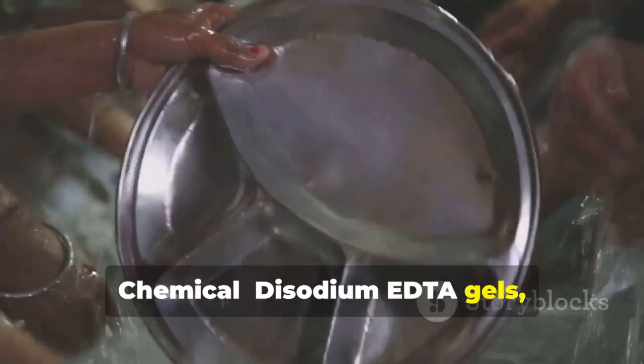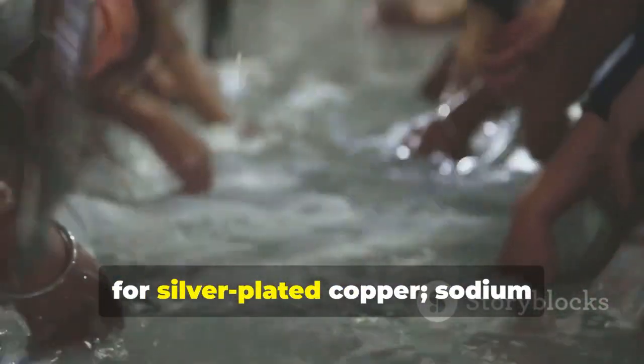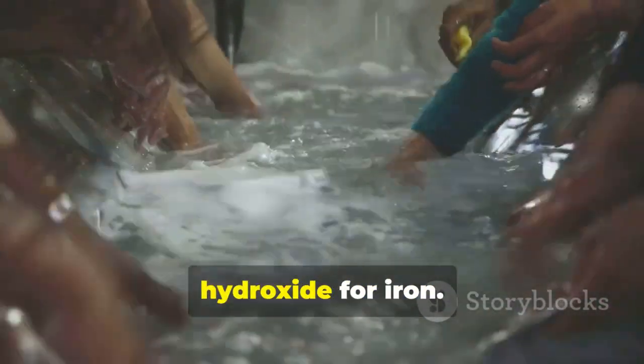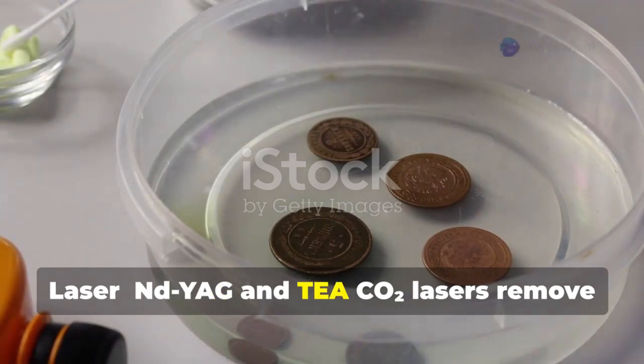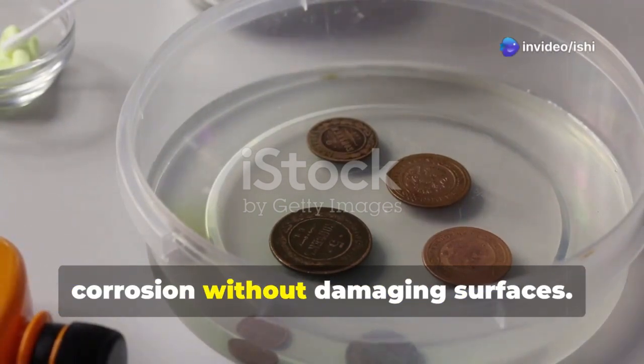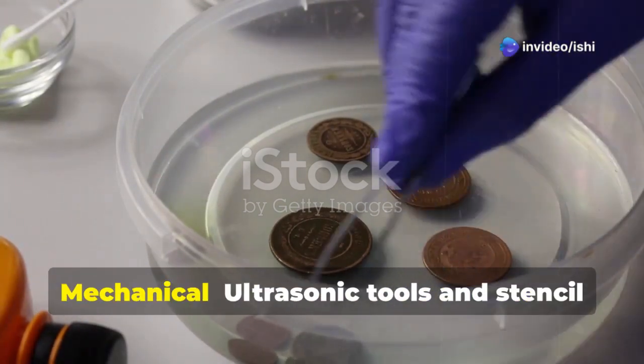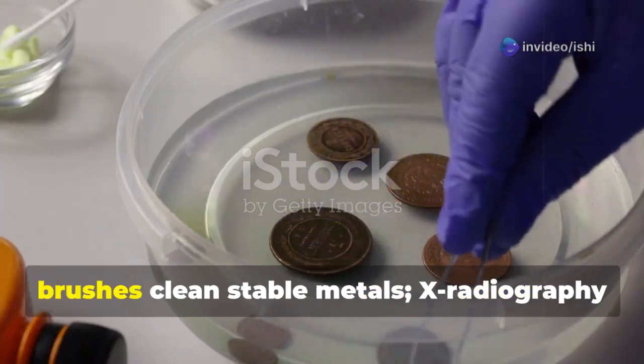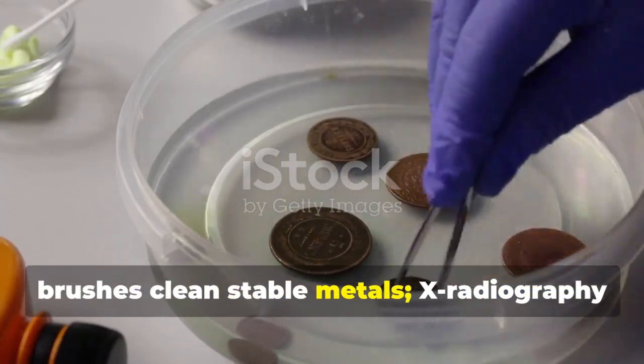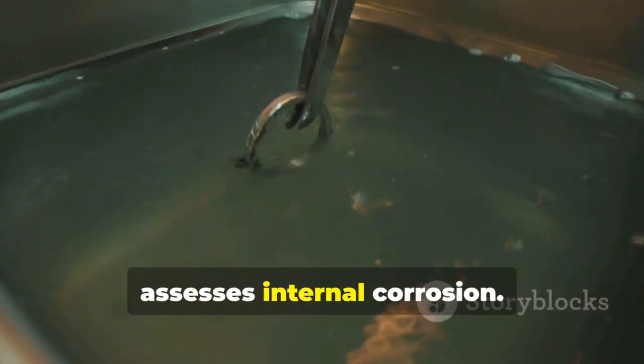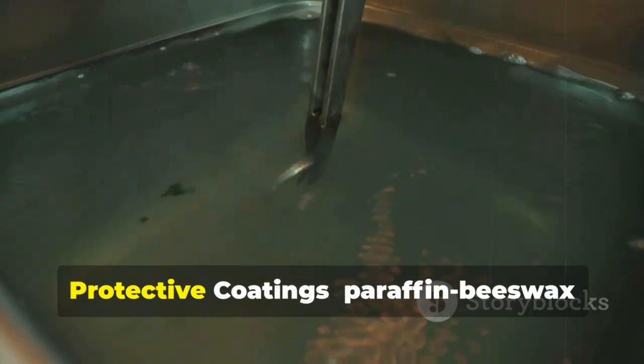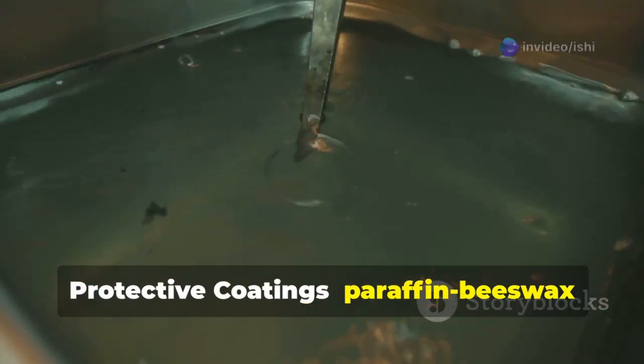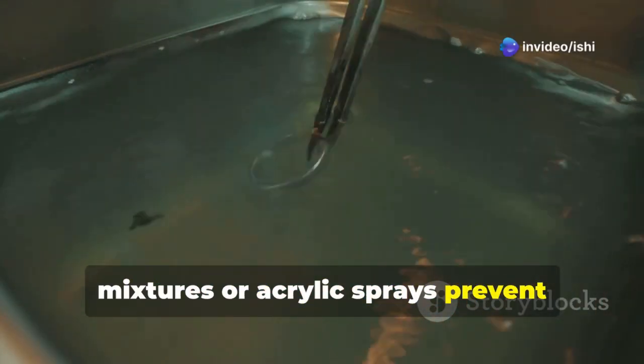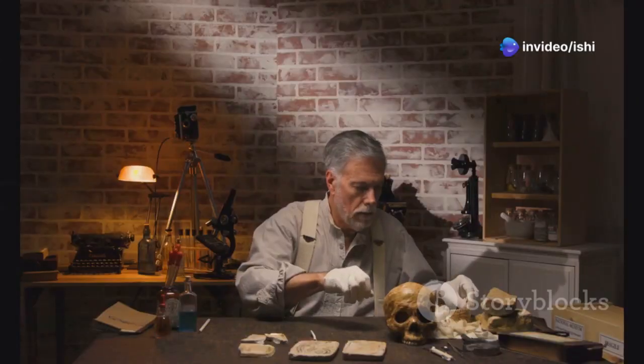Chemical treatments include disodium EDTA gels at 2 to 5% for silver-plated copper, and sodium hydroxide for iron. Nd:YAG and TEA CO2 lasers remove corrosion without damaging surfaces. Mechanical ultrasonic tools and stencil brushes clean stable metals. X-radiography assesses internal corrosion. Protective coatings, paraffin beeswax mixtures or acrylic sprays prevent moisture damage.